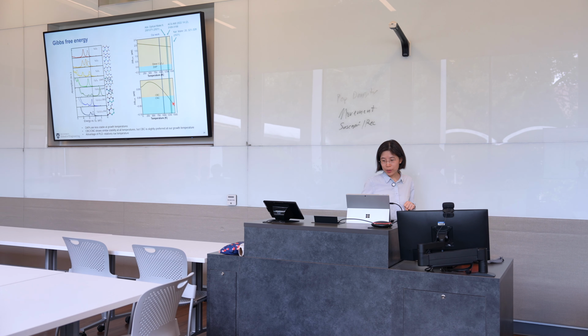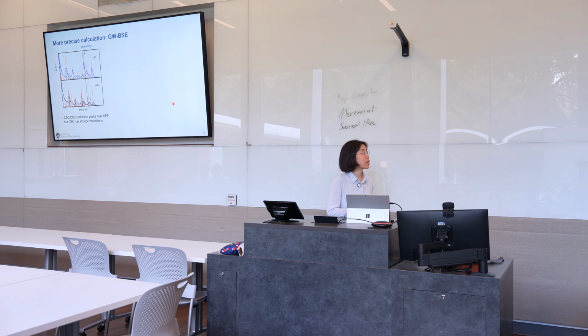To answer that question, we used a more precise calculation method called GW-BSE. Here we are still looking at the optical emission spectrum. This is CBC, this is CNC. You can see apparently CBC has a brighter emitter close to the experimental energy. So CBC is a better emitter, and it lines up better with our experiment.